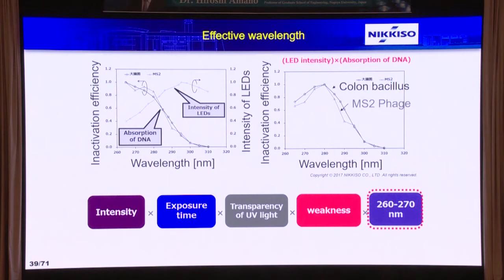Also, as I showed you before, the efficiency of LEDs drops gradually when shortening the wavelengths. And absorption of DNA or bacterium becomes maximum at 265 nanometers. So there is an optimum wavelength for deactivating the bacterium. It's around 280 nanometers.